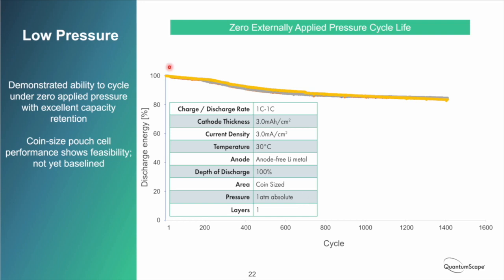And what you can see is that these cells are all performing quite well, cycling with gradual fade out to 1400 cycles, even under these 1C, 1C test conditions with zero pressure. Like I said, we haven't baselined this low pressure performance on our larger area cells, but I think it is a pretty compelling proof that the materials are capable. So this is something we'll be continuing to work on.